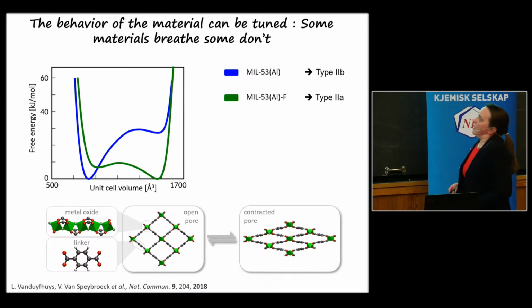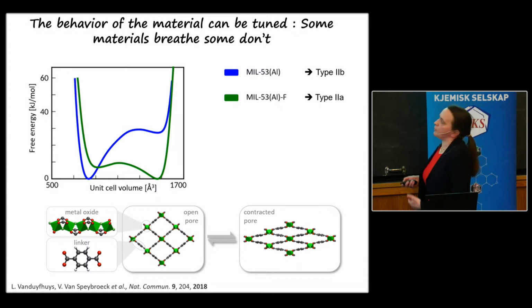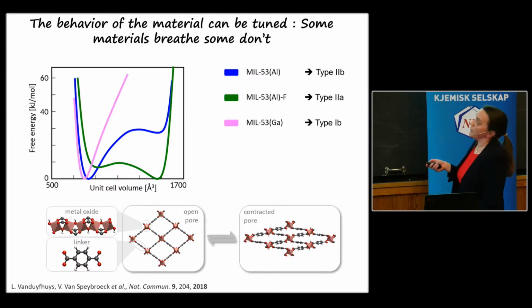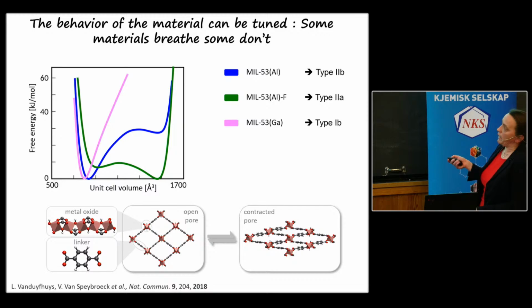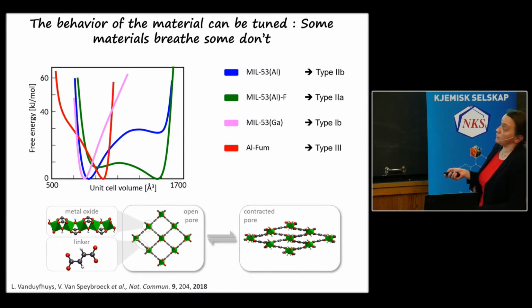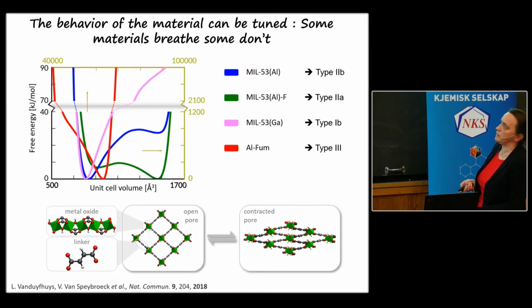When we introduce, for example, fluor into the framework, we can see that we can change the shape. Still two minima, but it's different. It will have another behavior. If we, for example, put gallium at these metal nodes, we can see that there will be no breathing anymore. It behaves like a spring. If we use another linker, we can see that it will become reversible breathing, open and closes. So you can really see that you can modulate this behavior by playing with the building blocks.